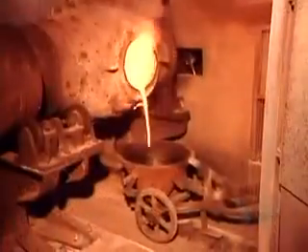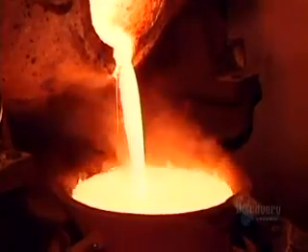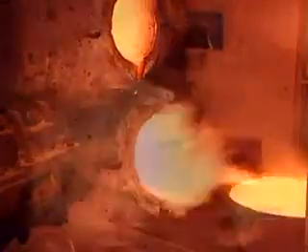They rotate the smelter so that the contents heat evenly. Over 2.5 hours, the heavier gold eventually sinks to the bottom, while the impurities, called slag, float to the surface. They pour out the slag, taking a sample to make sure it contains no gold. If it does, it goes back in until it's gold-free.